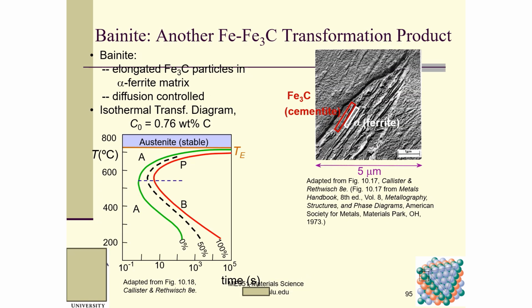Then bainite, another iron carbide transformation product. Bainite has elongated cementite particles in an alpha ferrite matrix. It is diffusion controlled, shown on the isothermal transformation diagram, isothermal meaning the temperature does not change. This is for this C0, 0.76 weight percent. Austenite is stable here, so we go down and then hold the temperature. Here is 100% pearlite, this is the fine pearlite. If we go down, we have the bainite.